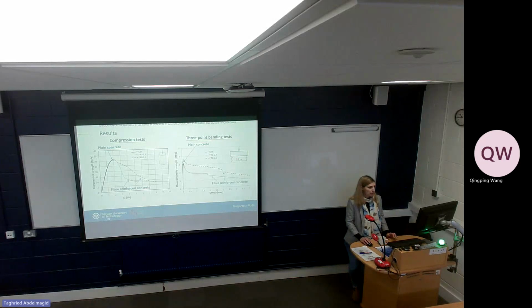So here is the black line. It's a plain concrete. So when you have the test, just as I said, it just breaks into 2 pieces and there is nothing going on. When you have the fiber reinforced concrete, then you can see that after achieving some deflection, or the crack mouth opening is getting bigger, so it's in truth cracked, it is still able to carry the loads. So here we get about 3, let's say, megapascal, and here with 1 millimeter of crack mouth opening deflection, we still get 2 megapascal. So it's very good. And when we get 1%, it's almost the same, yes? So this is very good.